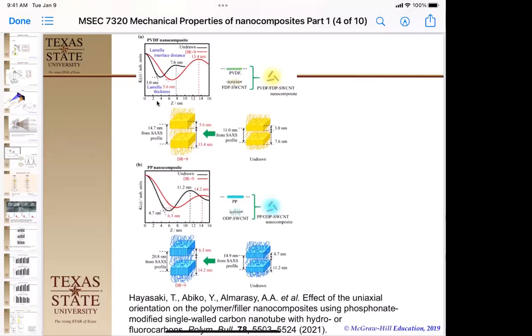So as we draw them out, we get this bigger distance between those rigid sections. Now remember, the rigid sections don't change much. The rubbery sections are the ones being elongated. And that's what we see in the change. And we see the same thing happen in the polypropylene. It starts a little bigger and gets a little bigger, but we have that same concept. Our polymer is aligning, and our nanocomposite is also probably aligning in that length, probably axially to the lamella. Questions on that? So again, really pretty pictures in this article.